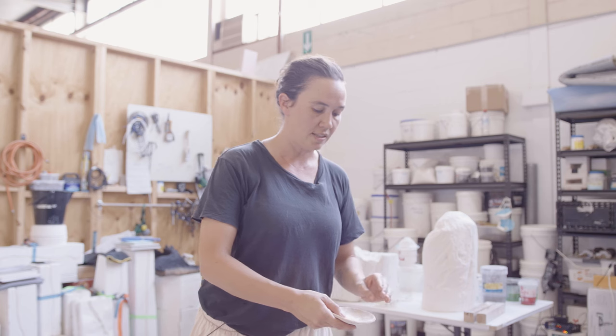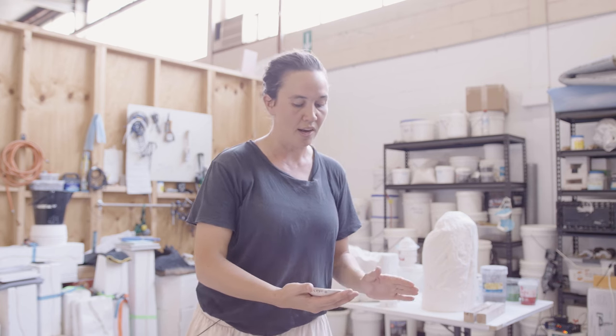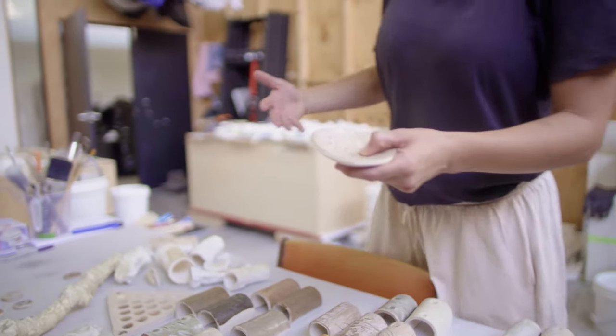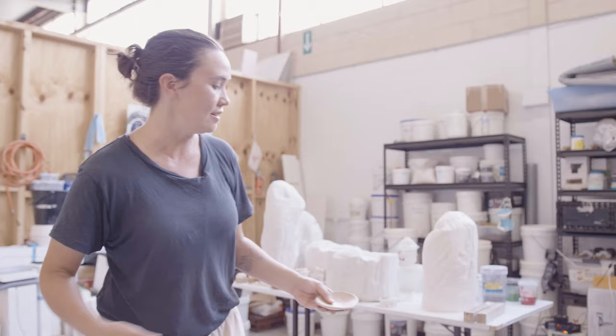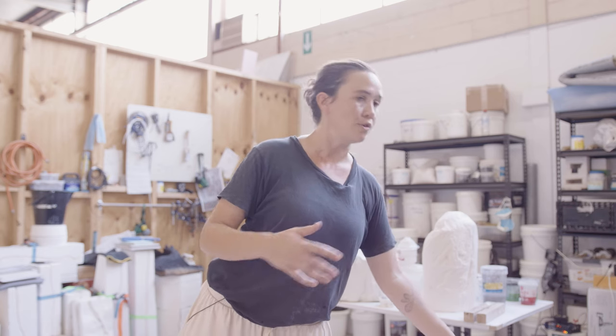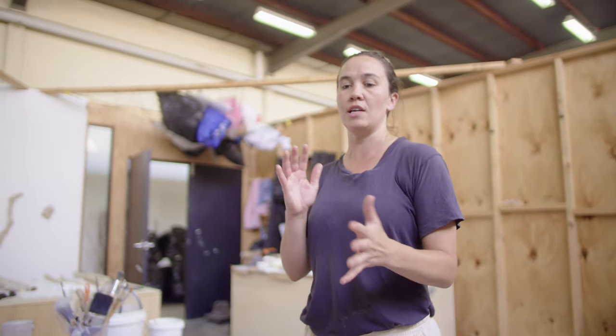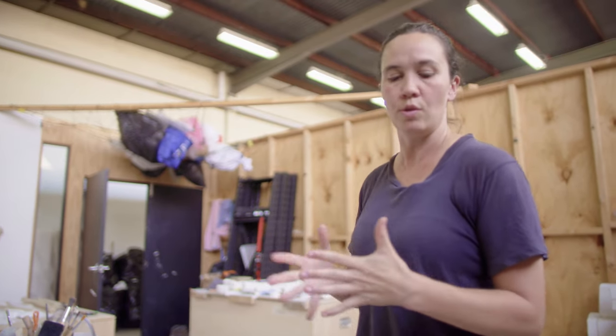a tree that I did in the flooded forests of Tasmania was a celery top pine, and it came out with more of a purple glaze. And purple is indicative of manganese dioxide. So I got the ashes tested, and that's something that I also do with every project, is to get the ash tested at a lab for its metal content. And in that particular case, it showed that that plant had more manganese dioxide in it compared to iron, for example, which usually dominates because it's so ubiquitous in the soils.